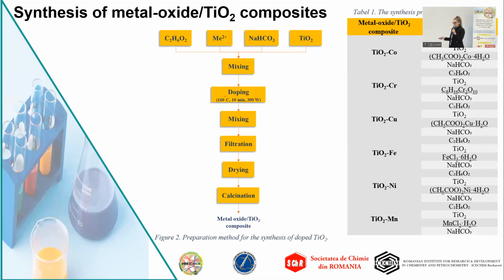The schematic synthesis of our metal oxide photocatalyst is shown in Figure 2, where titanium dioxide, sodium bicarbonate, and metal ions were mixed with ethylene glycol, the mixture being stirred well dispersed. The synthesis was carried out in a Discover 2.0 microwave flow reactor at 160 degrees Celsius for 10 minutes. After the reaction, the solution was subjected to mixing using stirring systems, followed by a filtering, drying, and calcining stage to obtain metal oxide photocatalyst.